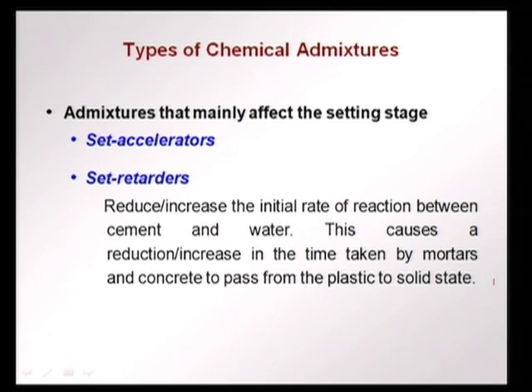So, this can reduce or increase the initial rate of reaction between the cement and water. They can slow down the initial rate of reaction or make the rate of reaction go faster, and this can cause a reduction or increase in the time taken by the mortar or concrete to pass from the plastic state to a solid state.